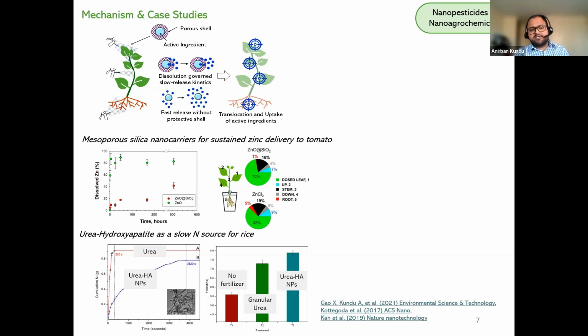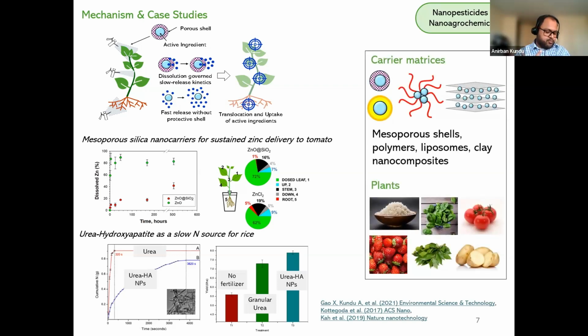What I really like about this study is they did experiments in the field, right? So if you look at the figure on the right, they found that when no fertilizer was applied, the yield was much less compared to when only granular urea was applied. So this is the conventional fertilizer source versus when urea hydroxyapatite nanoparticles were applied. So this sort of tells you that if you have a way of supplying the active ingredient over a period of time to the crop, then over a period of time, the productivity, the yield of the crop increases. And this is important because not only are you having an increased yield of the crop, but you're also making sure you're not wasting nutrients.